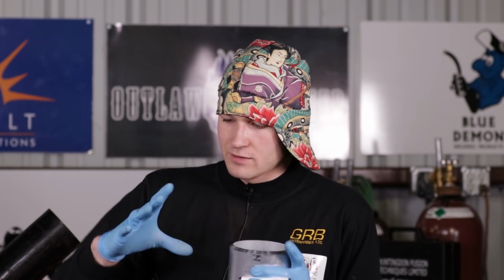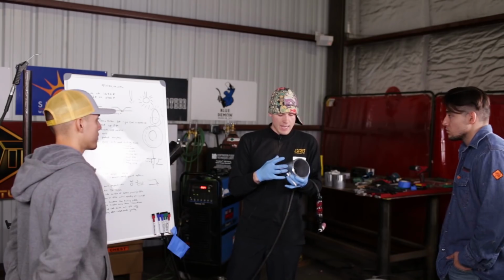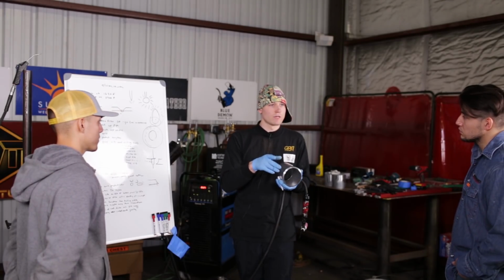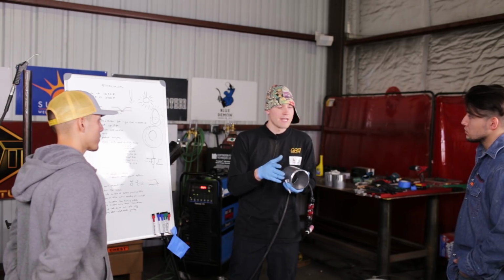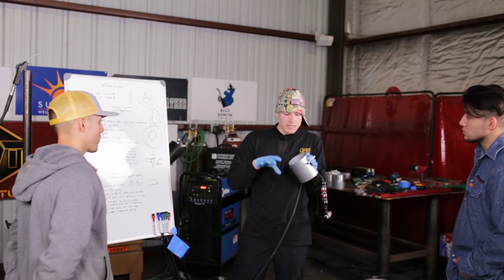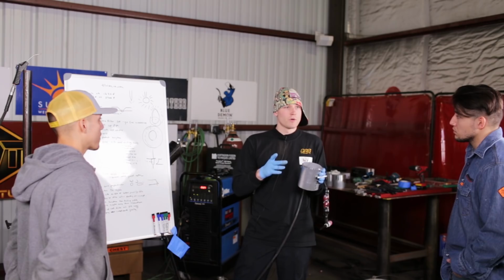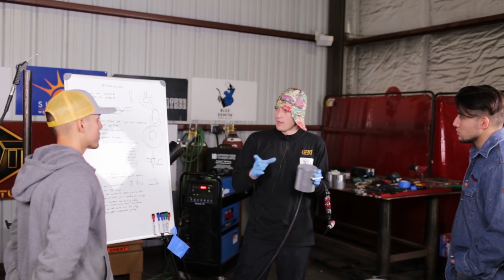I just cannot keep welding, because the weld puddle does not burn out the oxides. The oxides just fuse and mix in with the weld puddle, and they'll always be there. And in the application where it's vibrating, and even if you go through a nick break test, eventually it's just going to crack because there's no integrity in the weld puddle. Because the oxides, and this is the thing that separates aluminum from other metals, melt at such a high temperature they always have to be removed.